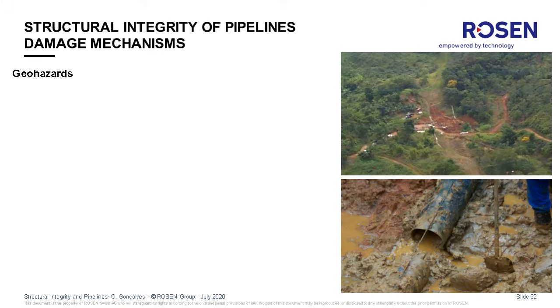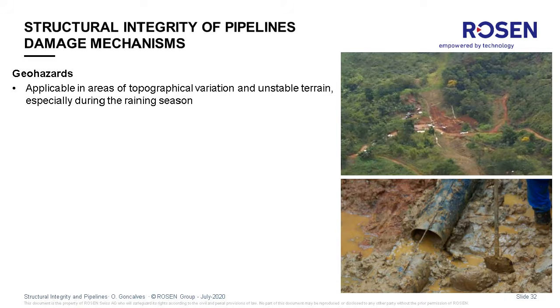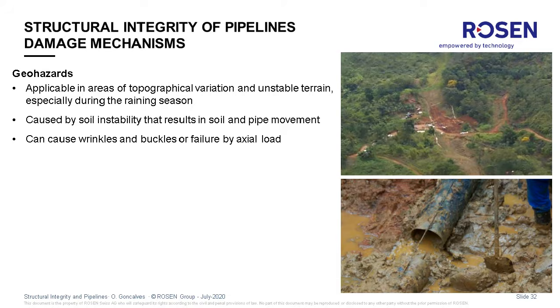Now, showing geohazards, which is basically when the soil, especially when there's a lot of water from raining, becomes unstable, and at some point there might be some soil movement, and then you have additional stresses to your pipeline that, if they are sideways, can cause wrinkles or buckles, and if they are in the axial direction, can cause a collapse, which is what's being shown in the picture, where the pipeline was basically severed.